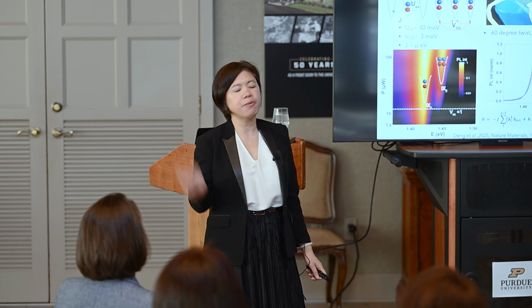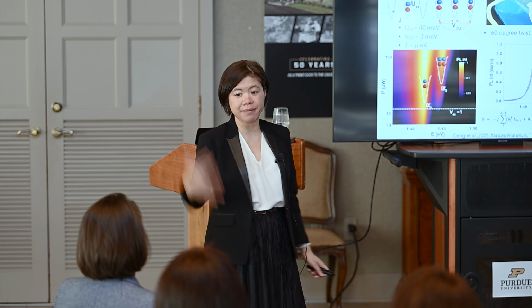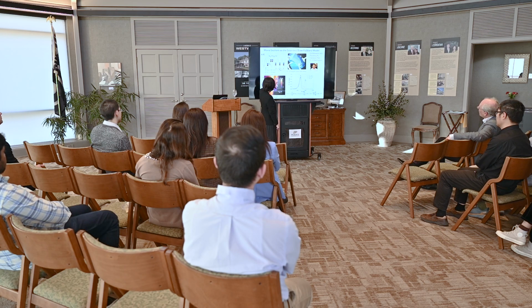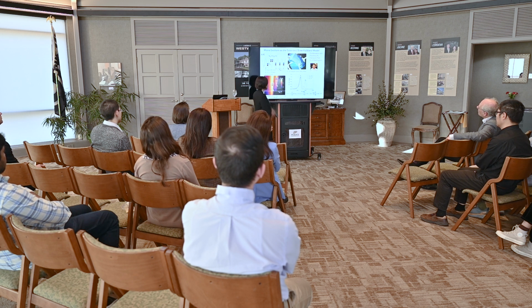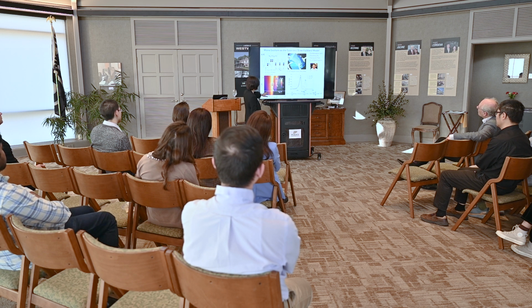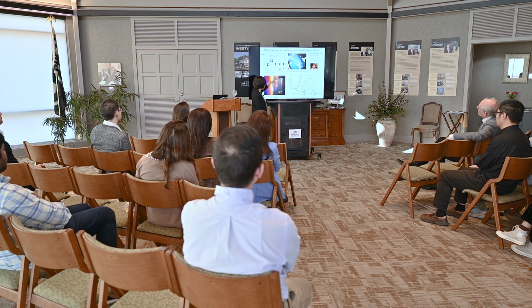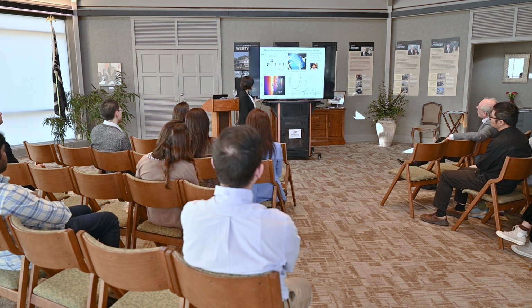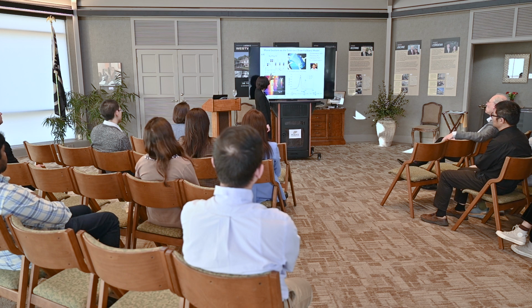And if you put in an additional particle, they would have to go to a different state, because, again, this is coming from the quantum effect. And so we can also determine the tunneling factor by measuring the motion of the excitons when they are very dilute. And so we know that now U is much larger than J, so we're going to see a crystallization, or an insulator state.